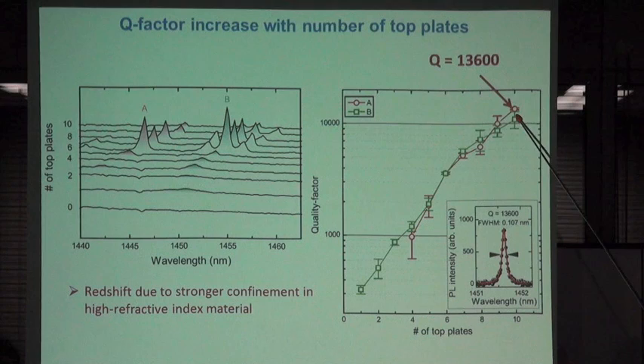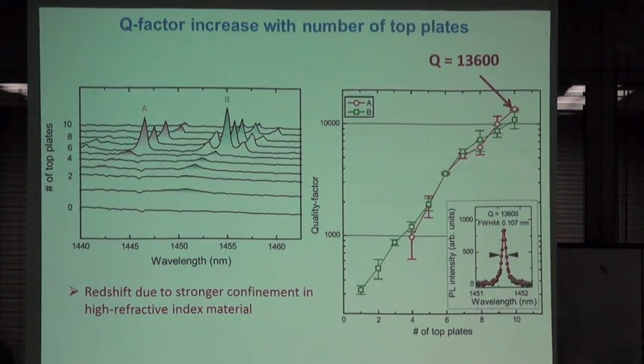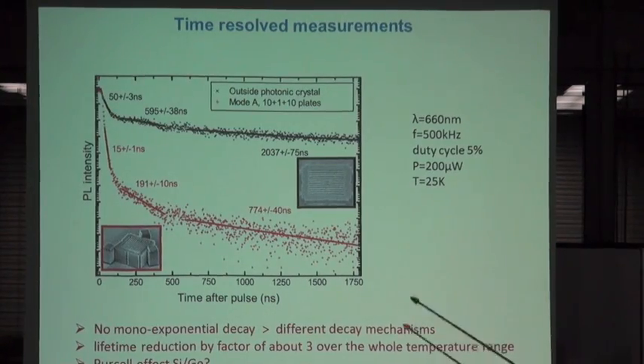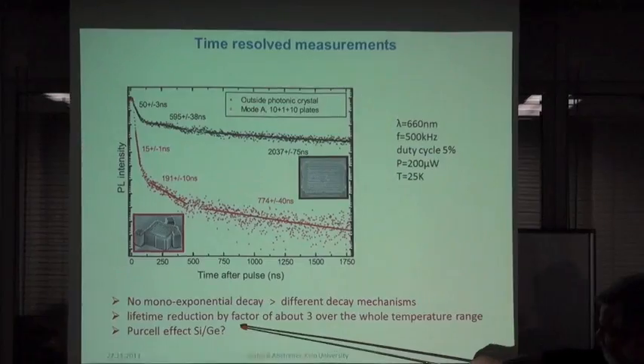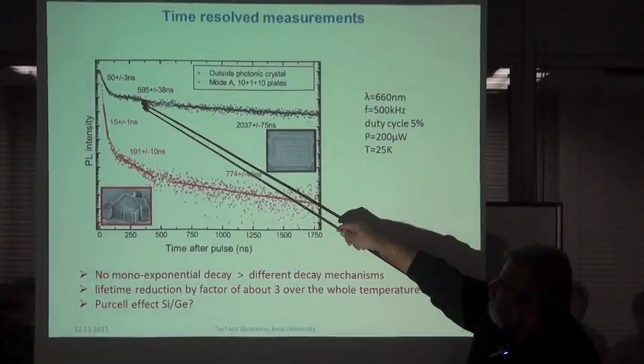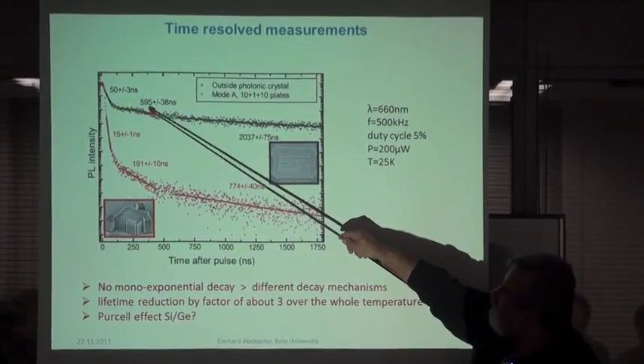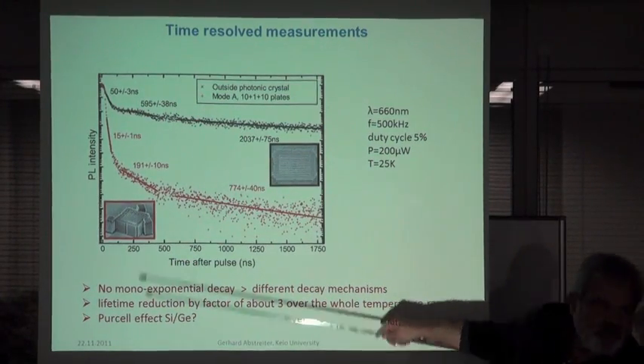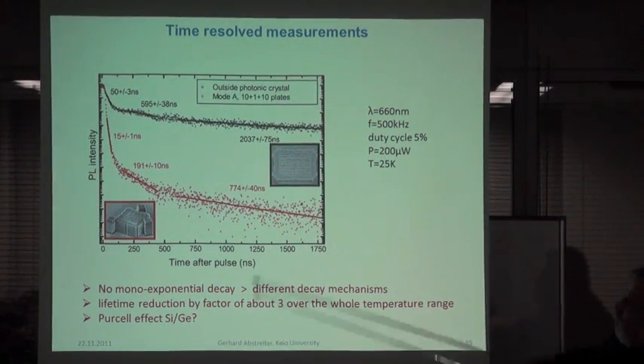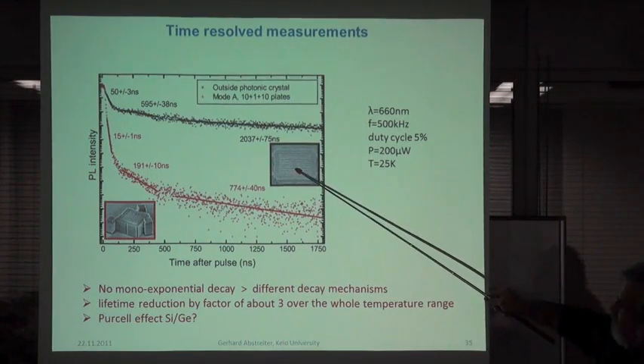And this is close to where you can also have strong coupling in this system, if we would have a good emitter. Germanium is not a good emitter. We thought maybe bismuth is a good emitter in this cavity. But this is the highest Q measured so far in such 3-dimensional photonic crystals in silicon. And actually, this is for the first time also that we think we have evidence already for Purcell effect. If we do the time-dependent measurement, we get the shortening of the lifetime also by a factor of 3 from the mode to the reference sample, just the platelet with the defect cavity.